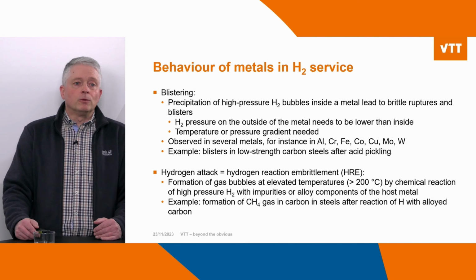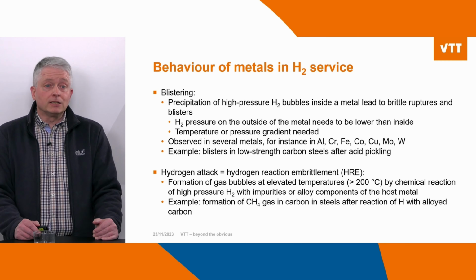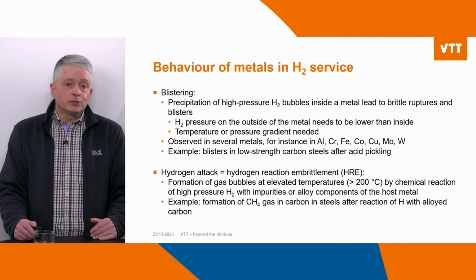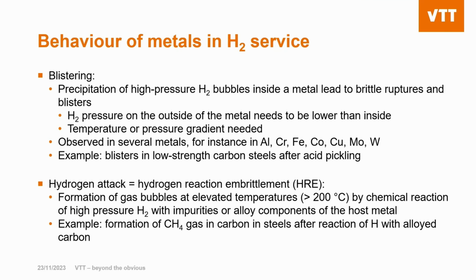What else can happen? It's possible that we observe blistering when metals are in contact with hydrogen. Especially with high pressure hydrogen, bubbles can form inside the metal and cause brittle ruptures and blisters. Usually here the hydrogen pressure outside of the metal has to be lower than inside the metal. There usually needs to be a temperature or pressure gradient. Several metals are affected. A typical example would be blisters in low-strength carbon steels after acid pickling. That is something that is sometimes observed.